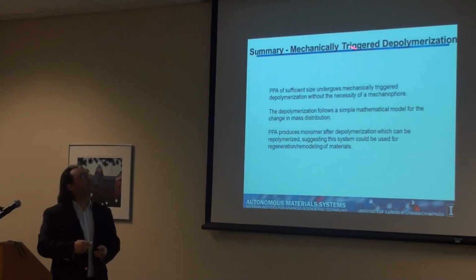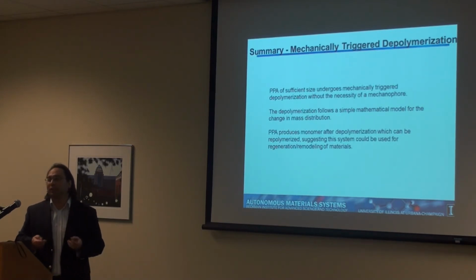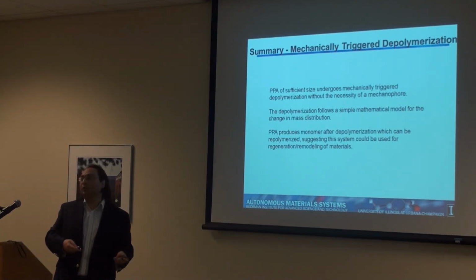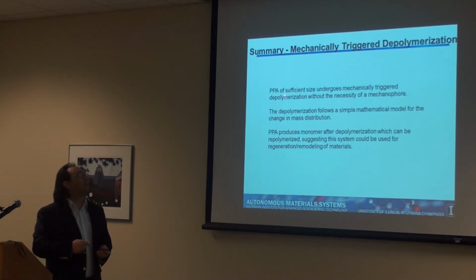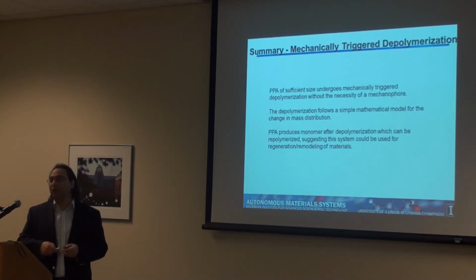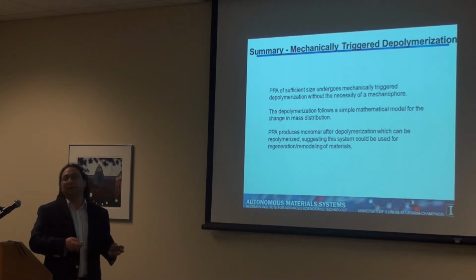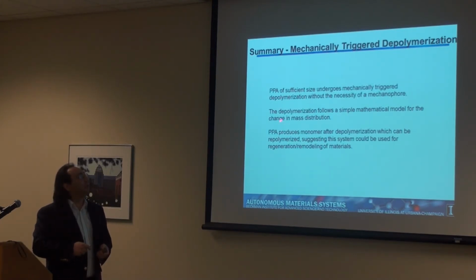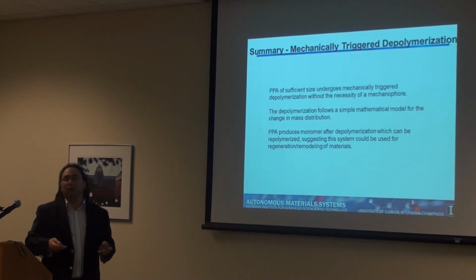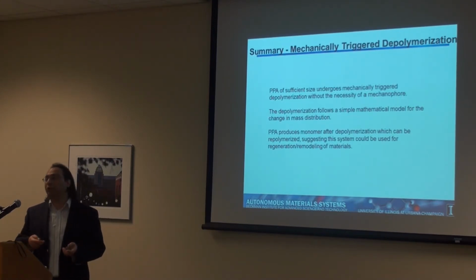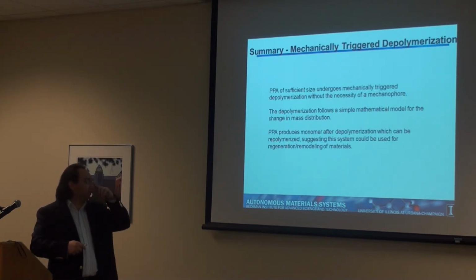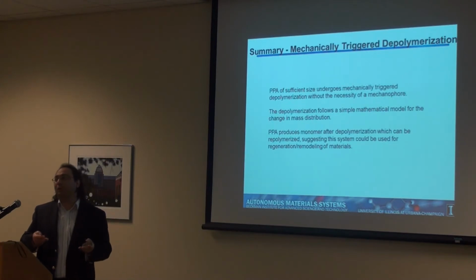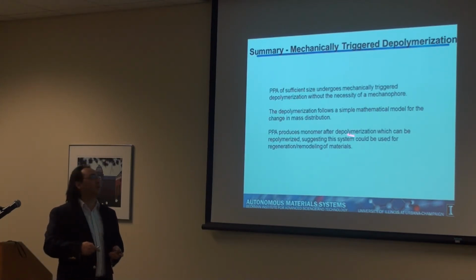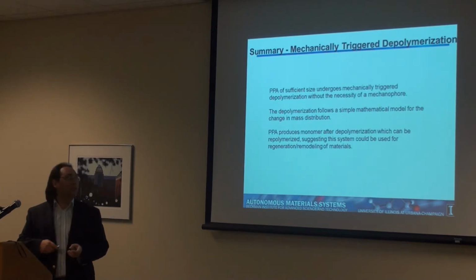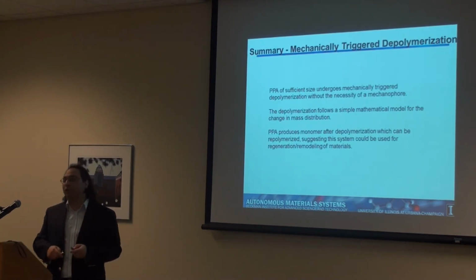So basically, we developed mechanically triggered depolymerization instead of a light-induced depolymerization or chemically induced depolymerization. Basically, having PPA of enough size, when you apply mechanical force, it undergoes depolymerization. And we don't need a mechanophore for that. We don't need the acid producing mechanophore in there. We can use a mathematical model to show how the molecular weight distribution is going to change. And basically, we show that the monomer that is produced by depolymerization can be repolymerized, so we can develop a completely new system that can have a material that can undergo regeneration and remodeling.